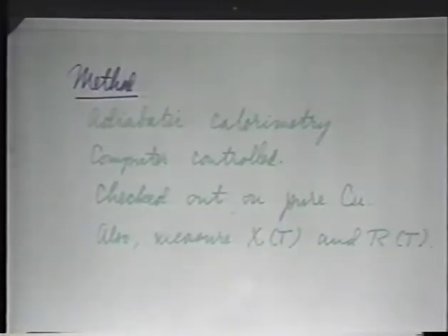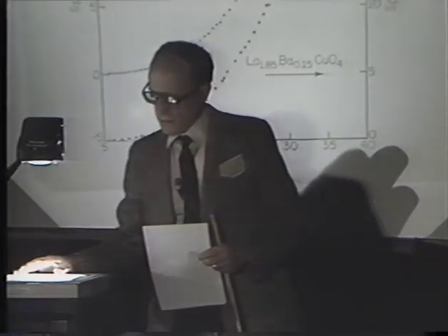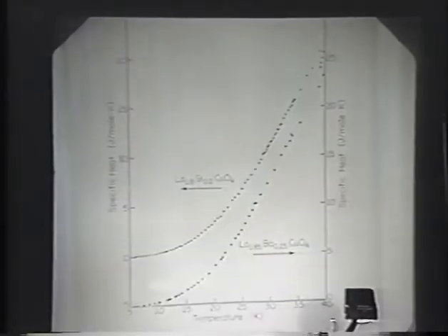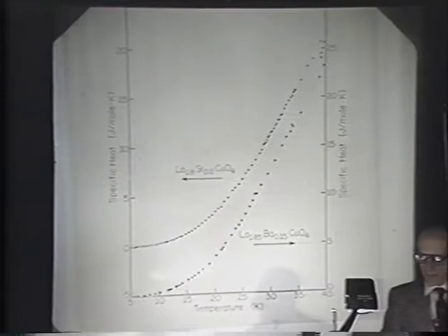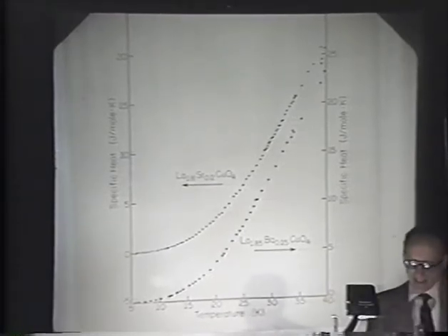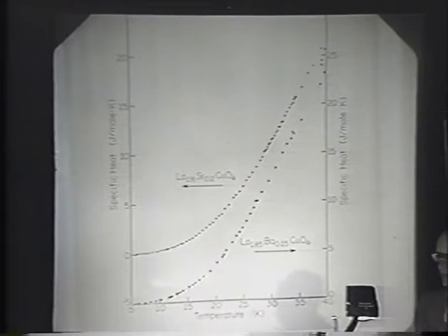We've used adiabatic calorimetry. We're new to the specific heat game, but we know that we're getting the right results because we measured pure copper and got the same answer as Clayton Swenson, who is one of the most careful workers in the field. Our calorimeter is run under computer control, and I'm going to show you the data. The calorimeter was put together to do specific heat work on Chevrel phase compounds. The sensitivity poops out as you get up toward 40 degrees, and so you start to get scatter up there. But we have some pretty nice data for which we're grateful.